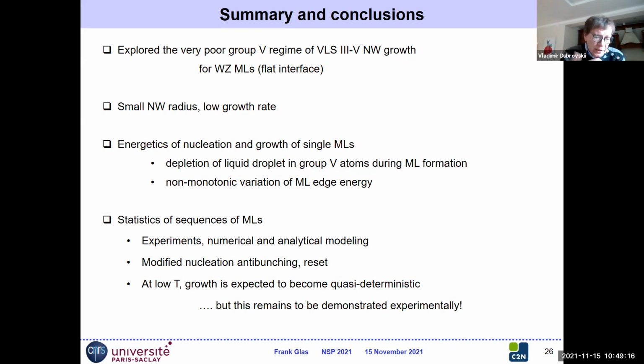So basically, you have explained perfectly that if the mother phase is very small, we can have the stopping size. And this has been demonstrated also experimentally, which is very nice. So then, at stopping size, the supersaturation is 0. And then basically we can say that when it stops the fractional monolayer, then it stays at a stopping size at 0 supersaturation, roughly. And that's why it grows at the rate of refill.